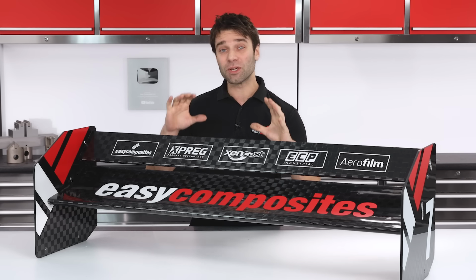This adhesive can then be spread evenly over the end plates at around 500 grams per square metre. A notch spreader can be useful for this, but on these small parts I find a brush works just fine. By slightly sliding the honeycomb once in position, you will force the adhesive onto the side walls of the cells, and this will help to form a fillet joint with a large surface area. The same sliding method can be used once the top plate is in position.